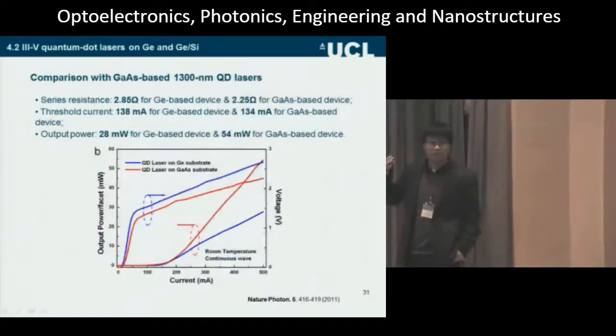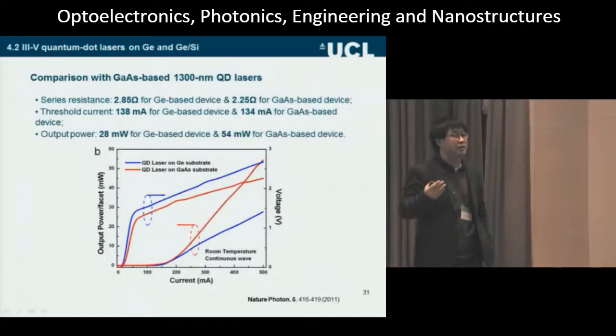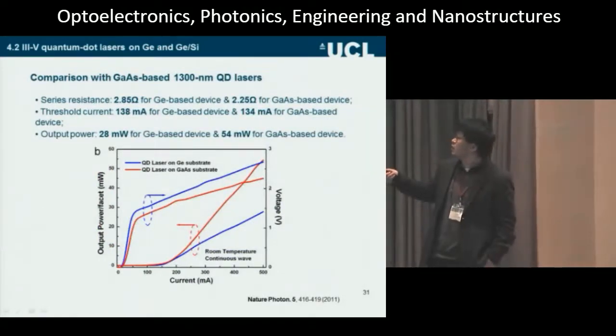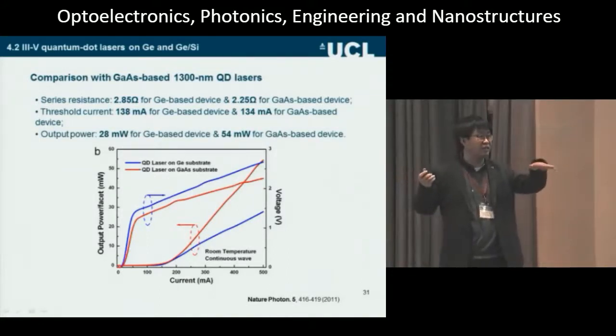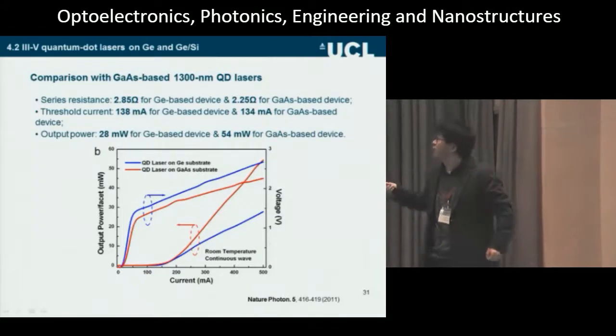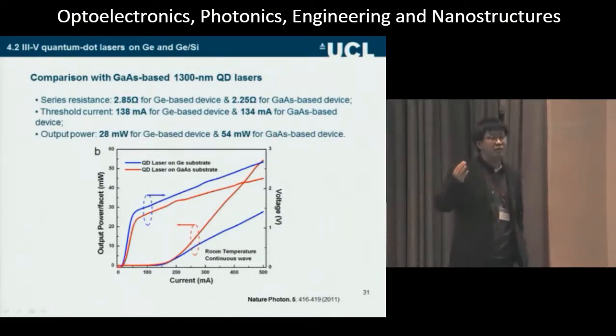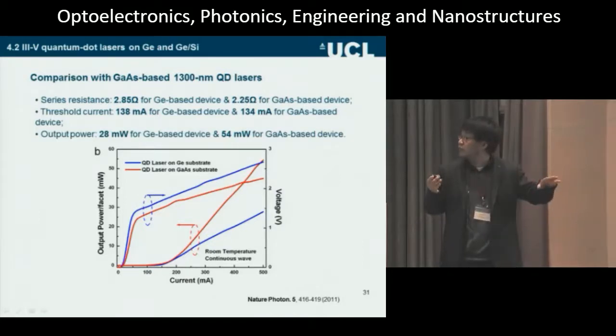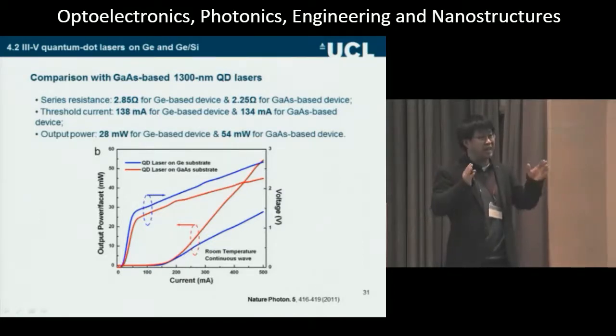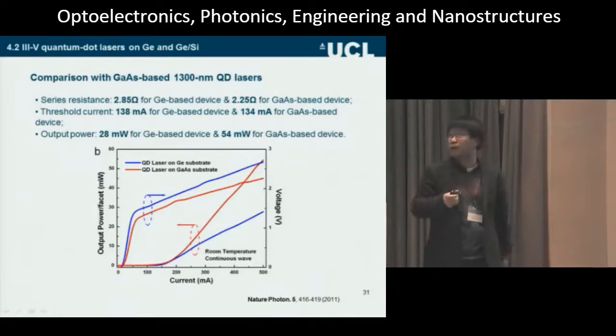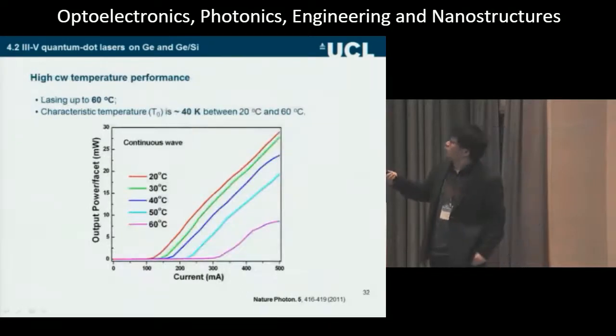We did grow a quantum dot laser on gallium arsenide at that time to compare with each other. Actually, the resistance is slightly higher because we have interface defects between gallium arsenide and germanium. And the only problem with the power is it's about half. Because it's an off-cut substrate, the surface is not very flat, and also the cavity not very perfect. You do lose some power. For the first device, we get CW operation up to 60 degrees.